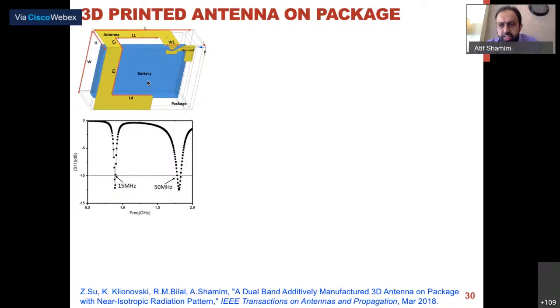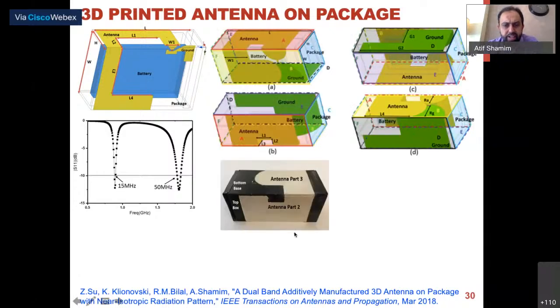So here you see the simulated and measured results. We had struggled a lot to get the wider bandwidth on the higher band. So the 900 megahertz and the 1.8 gigahertz, and we had to do some tricks. So we got good bandwidth for GSM at both bands, 8.9% and 33%. And more importantly, the gain variation is less than or close to 7 dBs, which is kind of a standard. So you can see it's like a kind of a near isotropic pattern. Okay, I'm rushing a little bit.